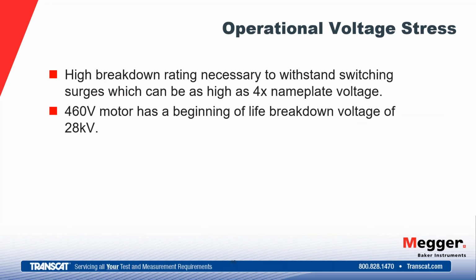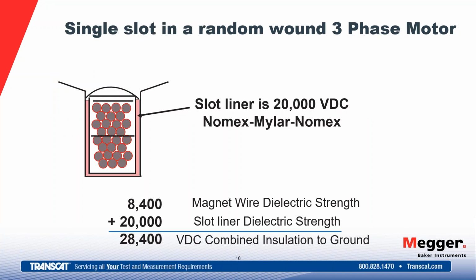So operational voltage, again, needs a high breakdown rating to withstand the switching surges, which can be as high as 4 times nameplate. For instance, for a 460 volt motor, at the beginning of life, its breakdown voltage is 28 kV. So here's where we kind of come from those numbers.